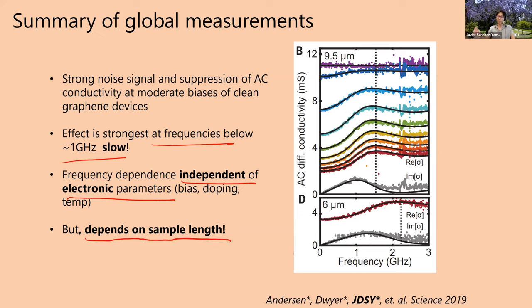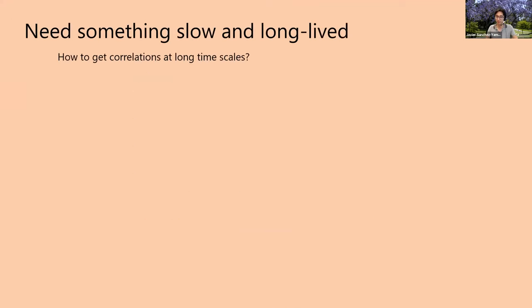So if we make the sample shorter, that's what we did in this data set here. We have a 6-micron device instead of 9.5 microns. And we see that this roll-off occurs at a higher frequency. Make it shorter, higher frequency. So this is what made us think about phonons, because phonons are slow, yet they may depend on the length of your sample.